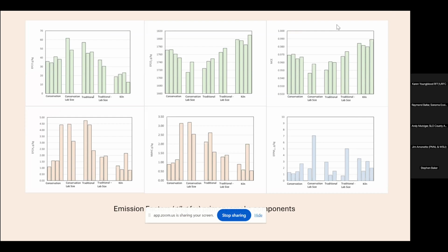So the product of all this work is the emission factors for various species. Let's look up at the left-hand side at the emission factors of CO. We see that the kiln burns had the lowest emission factors for CO. The conservation emission factors for CO were lower than the traditional, but again, the kilns were the lowest. As would be expected, the CO2 emission factors for the kilns were the highest, and the conservation were a bit higher than the traditional. MCE is a ratio of that, so again, the kiln MCEs are higher than the other two.